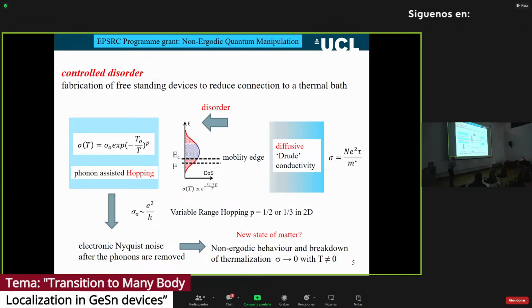What happens as we reduce the chemical potential deeper into the band is that the transport mechanism can go over to hopping. So the charge now no longer, well, when we have a mobility edge, we can still get diffusion. So we get a kind of thermal excitation to the mobility edge, and the carriers have a lifetime. They can diffuse at the mobility edge with a particular lifetime. When we reduce the chemical potential, we have the possibility of hopping now. And we've still got this temperature dependence of the conductivity, T0.